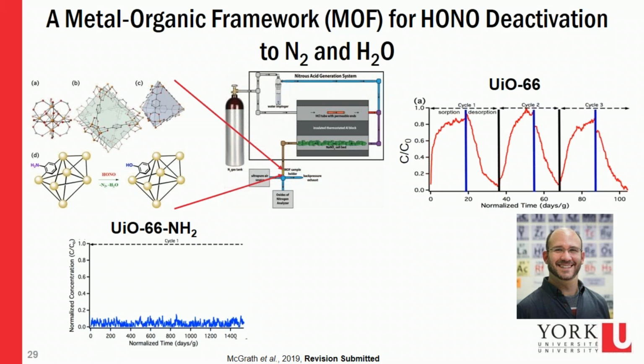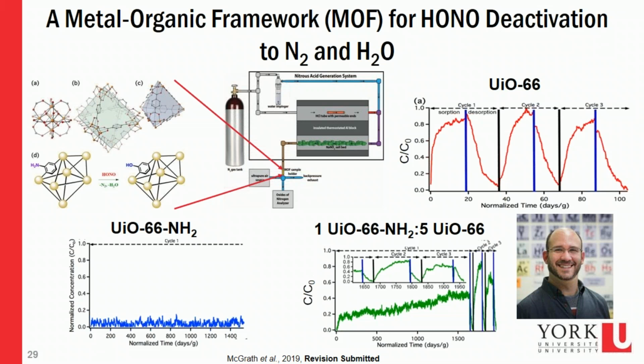Here we're at 1400, and we don't have any HONO coming through our metal organic framework with the same amount put into that tube that we're trying to break through on. The chemistry is very effective at scrubbing HONO. In order to see anything coming through, we had to start to dilute it with the unfunctionalized version in order to actually see the consumption of all the amine functional groups in it. So we have so much porosity, we have so many organic functional groups to do the reactivity within this metal organic framework that's very, very selective for scrubbing HONO. When we dilute that, we can then start to see a HONO breakthrough.